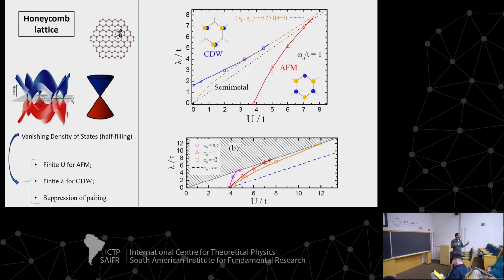In the sense that these critical lines in the honeycomb, in graphene, let's put it this way, are quite dependent on the frequencies of the phonons that you have in your background. So we cannot disregard it, because depending on the kind of the phonons and the energy of these phonons, these critical points may change a lot. So if you are interested to analyze graphene, and in particular twisted bilayer graphene, my suggestion is, please do not disregard the phonons. They can be important to your analysis.